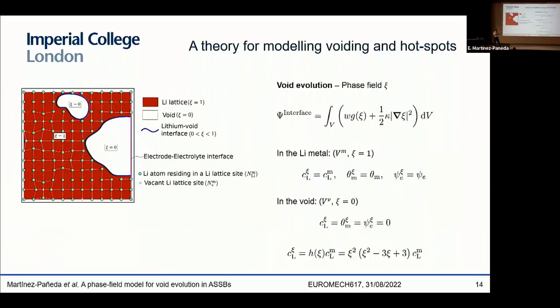Then if we're trying to model the void evolution, what we have is the phase field, which describes this evolution of voids due to the annihilation and nucleation of vacancies. Therefore, you have this phase field auxiliary variable, or order parameter, that will be 0 inside of the voids and 1 outside of the voids, and they will be interpolated with this interpolation function h in between. So of course, inside of the void you have no strain energy density, you have no concentration, but in the lithium metal all those quantities become relevant again, and you interpolate them with this interpolation function.